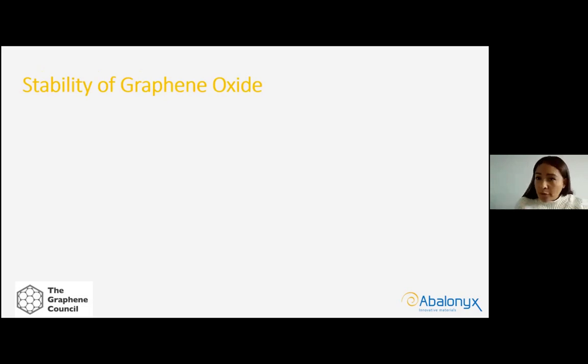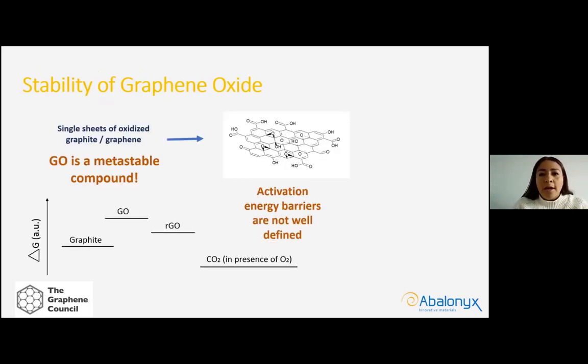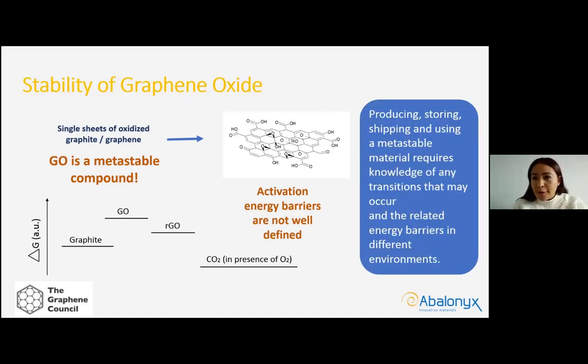So now I want to talk about the stability of this material. I have shown you this diagram before. So here we have the graphene oxide, and we know that we're adding energy to the graphite to get this graphene oxide. But then what happens after that? It's been suggested that spontaneous changes happen in the surface of the material, making this compound a metastable one. And we also know that the energy barriers of these changes are not well defined. And why am I telling you this? Because producing, storing, shipping, and working with a metastable material requires good knowledge about the changes that can happen under different environments.